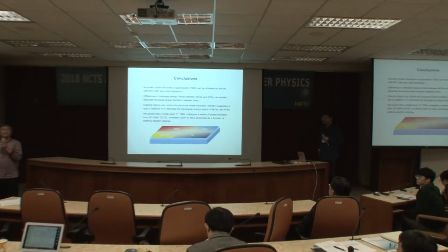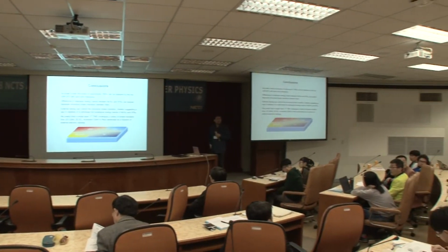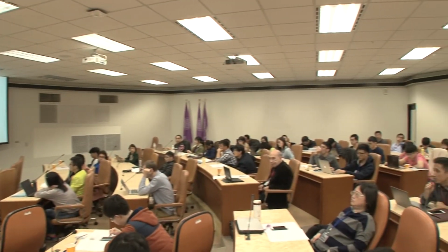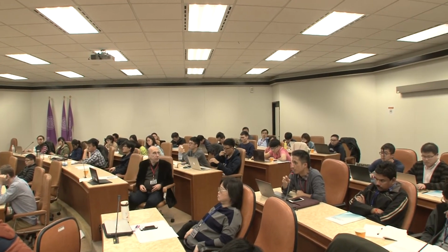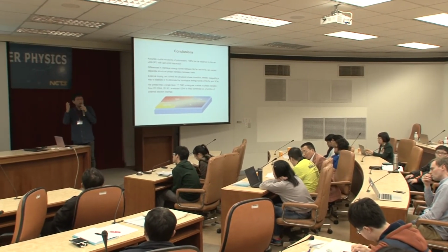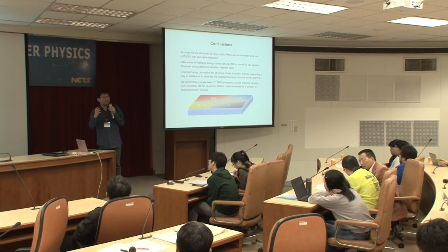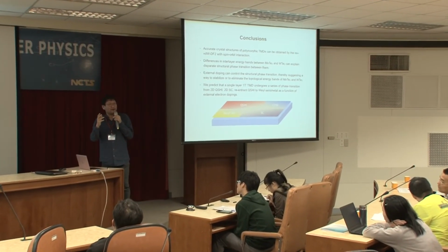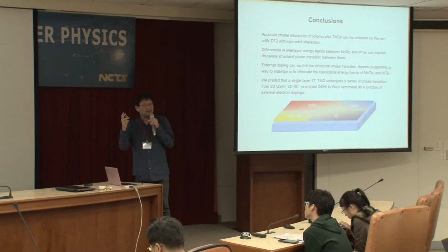Question or comment? Please. So in the Weyl semimetal phase of the monolayer TMD, I wonder what symmetry protects your Weyl node, or can it actually be easily gapped? What, 1T prime? Yeah, actually the last. Yeah. 1T prime single layer is essentially a spin-orbit induced gap. Okay, the band is inverted, so it doesn't survive with the inclusion of spin-orbit interaction. So it's just a trivial quantum spin Hall insulator. It's a prototypical Kane-Mele quantum spin Hall insulator.